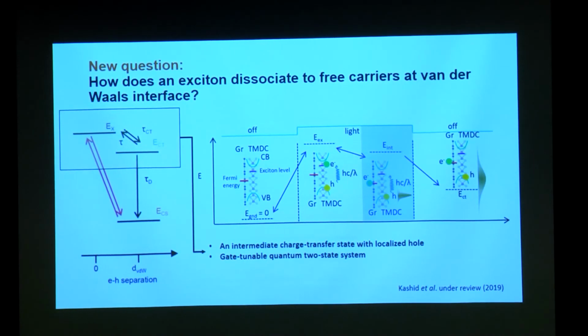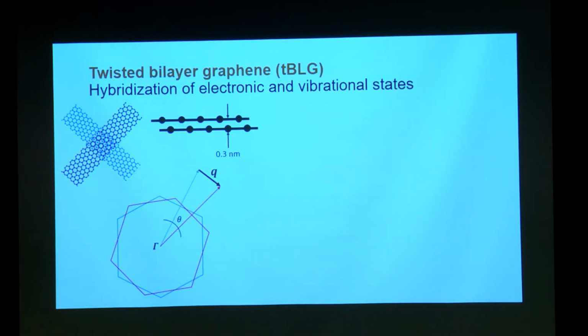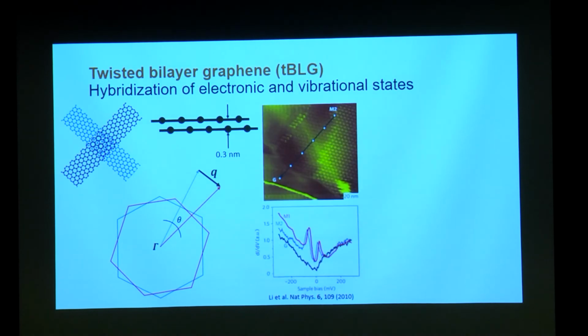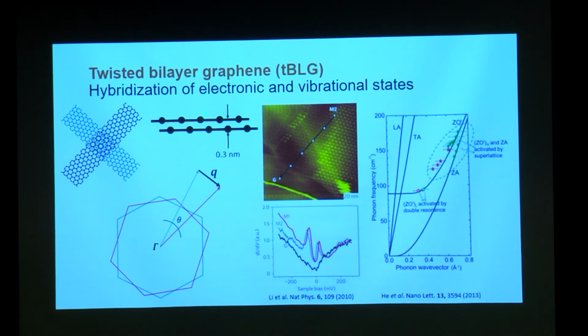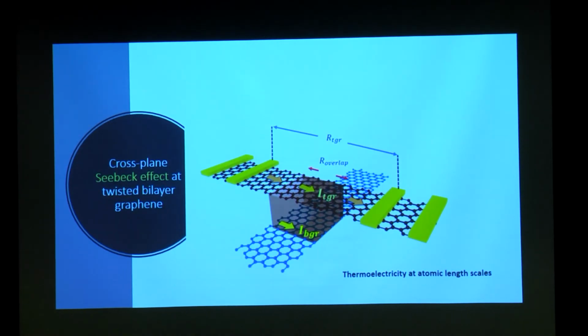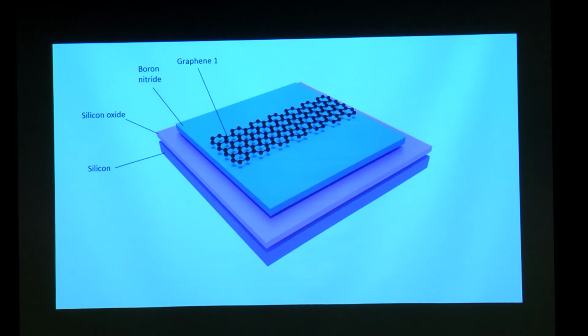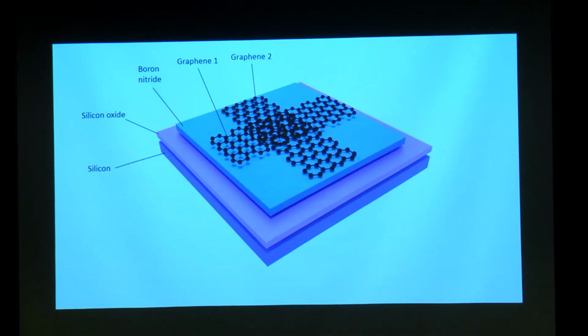Now, I think I'm going to skip this part because today I lost some time initially, but we did look at this. This is what I had, another example of charge transfer which leads to a very interesting thermoelectric transport in such bilayers of graphene, where the hybridization of charge and phonons leads to very interesting layer and twist dependent thermoelectric properties. I'm not going to say this at all, but because of our ability to make heterostructures, we can make these kind of graphene bilayers, in which you can get access to two layers which are separated by 0.3 to 0.5 nanometer, and you can look at electrical transport across these structures.